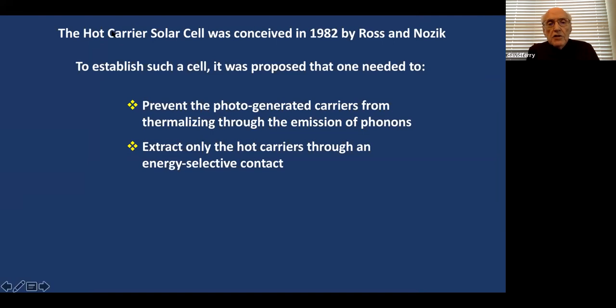Now, the hot carrier solar cell was conceived in 1982 by Ross and Nozik. Brilliant idea, good people. And to establish such a cell, it was proposed that one needed to prevent the thermalizing through the emission of phonons, cut off that phonon rattle down in the bands, right? By some mechanism or the other. One way that they talk about, as we'll see in a minute, is what's called a blockade. And I'll explain that too. And extract only the hot carriers through an energy selective contact, okay?